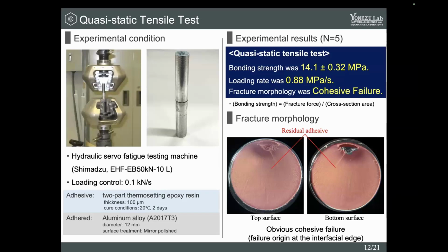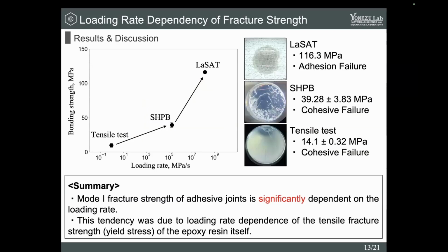In addition, we conducted quasi-static tensile test. As a result, in tensile test, bonding strength was determined as about 14 megapascal, and fracture morphology was cohesive failure. This is a relationship between loading rate and mode 1 fracture strength. Fracture strength was significantly dependent on the loading rate.